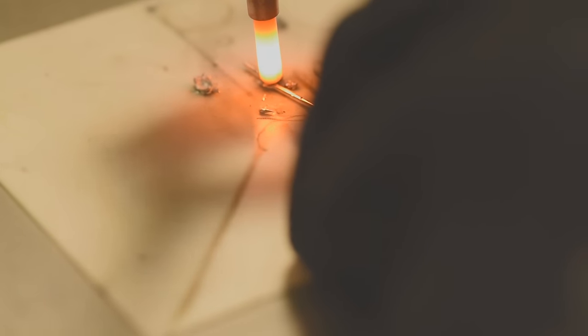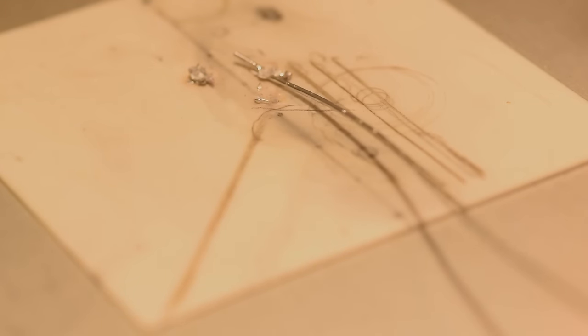So I did a quick experiment. I used a glow plug to try and forge weld aluminum wire to an aluminum oxide surface on an aluminum build plate. And here you can see that I have some success semi-solid forming this aluminum wire to its own blobs and to the aluminum oxide itself.